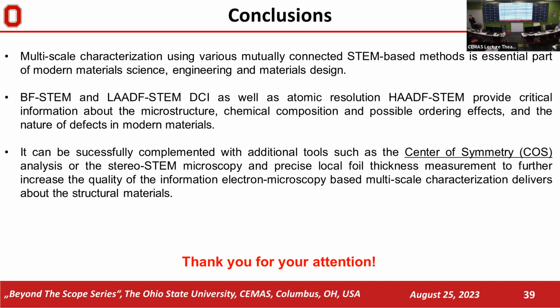I saw a question online. Abhishek is excited about trying this out himself, but he's also wondering: while long-range local ordering can be clearly identified using Stereostem, what are your thoughts on the possibilities of identifying short range ordering? Yeah, as I said, it's a very specific ordering which we empirically found we can detect. I was talking about chrome nickel based alloys here, and there are different types of ordering which obviously cannot be detected by this, and you have to use different techniques. There is energy filtered TEM, or 4D STEM is now being investigated, to see what kind of answer it can deliver for ordering.